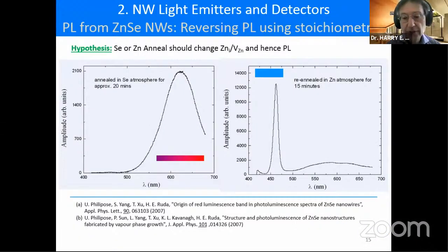So now comes the $1,000 question: can one engineer a response or a color one would like? And the answer is, if this is the mechanism, surely one could. So if we start with a zinc-rich grown nanowire, which is dominated by the blue emission, and we put it back in the chamber and anneal it in a selenium-rich atmosphere for 20 minutes, you see the left figure emerges. We've quenched off that blue emission, and we now have dominant red emission from the donor-acceptor pairs.